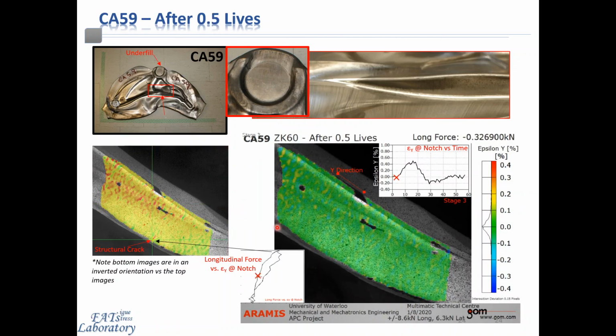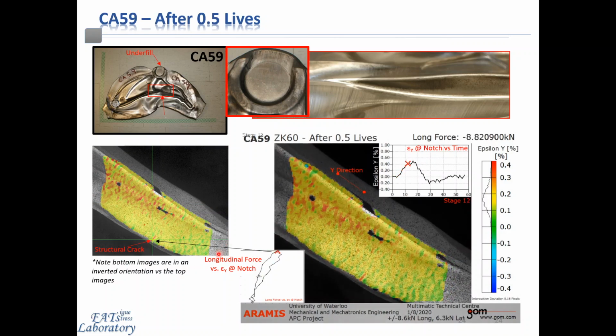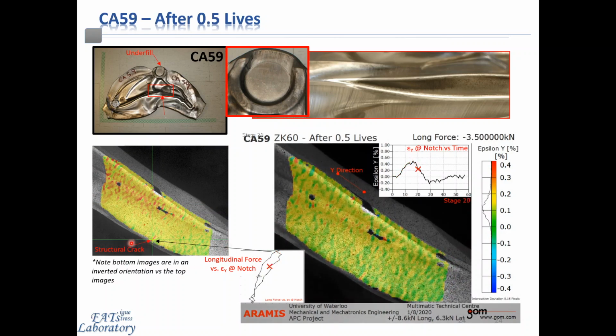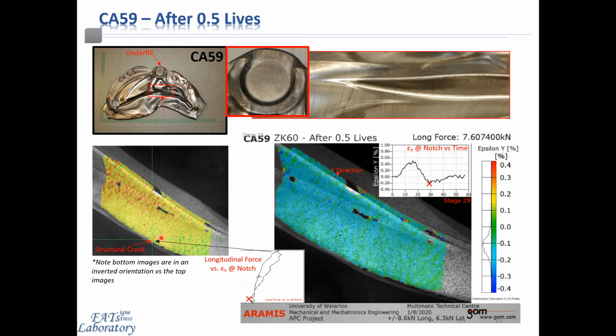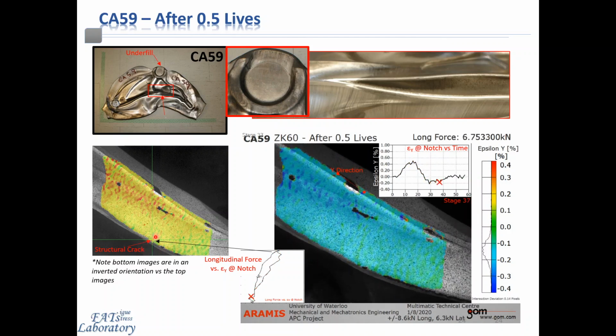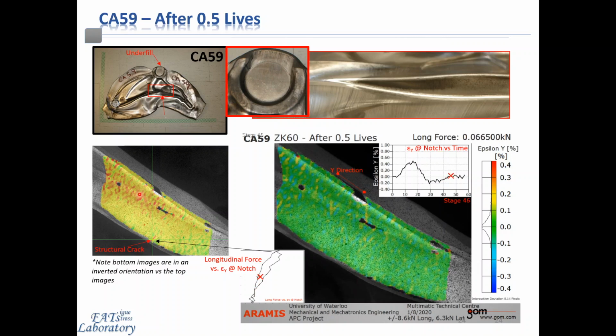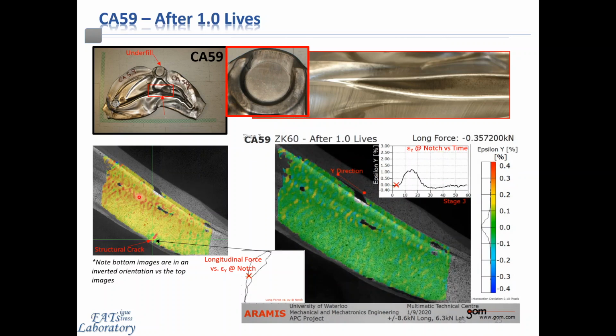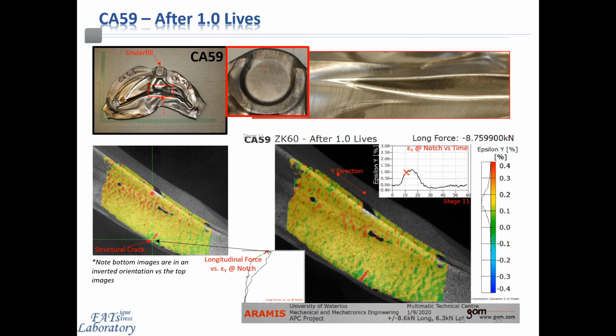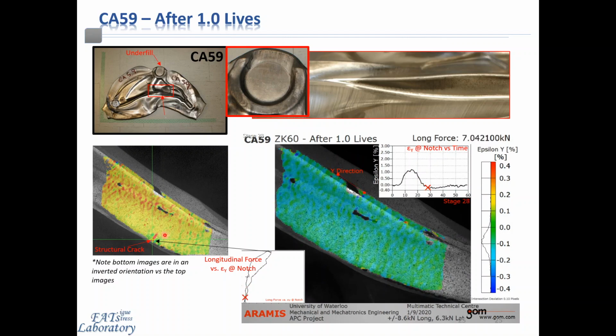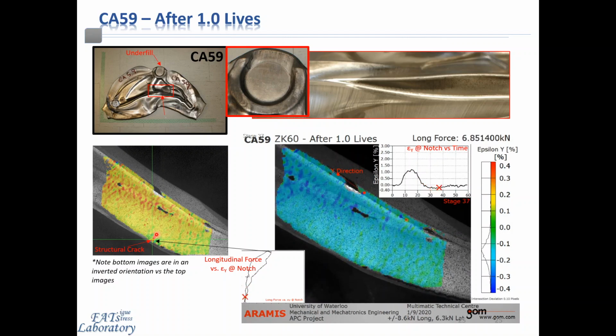However, now at 50% fatigue life, we can see that the strain localizes at a region indicated by the green crosshairs on the left here, shown at the cursor, which is a totally different location of the component than what we were observing, which was somewhere closer to here in the previous component. After 100% of the fatigue life, the crack, which previously nucleated, had grown larger in that particular location, which is totally different, as I mentioned again.